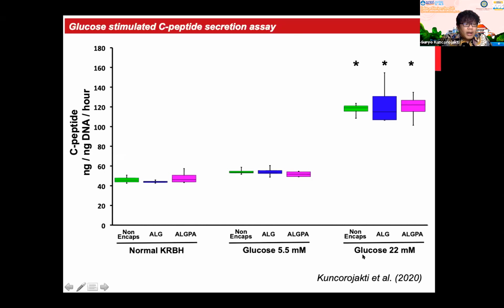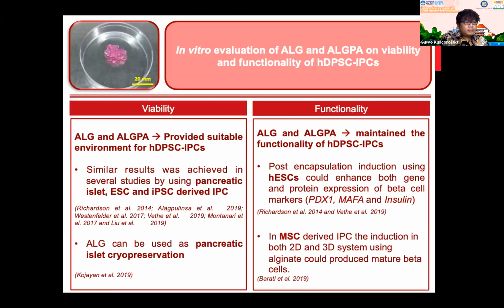When incubated under 22 millimolar of glucose solution in Krebs-Ringer buffer, a significant difference was also observed when compared with the C-peptide secretion in normal Krebs buffer and also glucose 5.5 millimolar in Krebs buffer. And from this study, the qualitative in vitro viability assessment of encapsulated human dental pulp stem cell derived IPC in alginate and alginate pluronic acid showed that both encapsulation platforms can provide a suitable environment for dental pulp stem cell derived IPC.